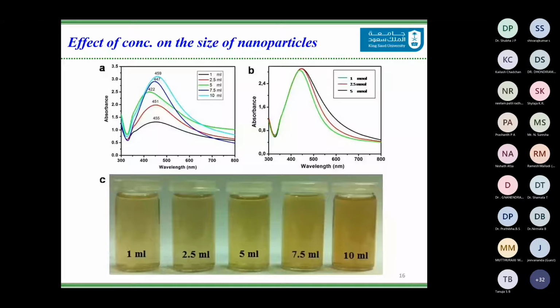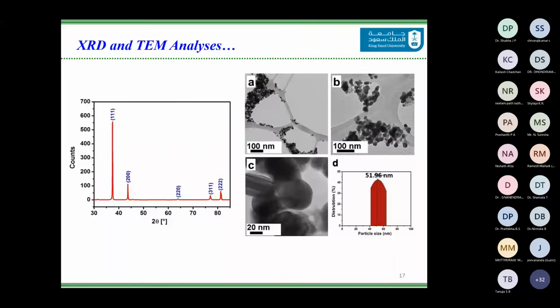Moving ahead, we subjected the obtained nanoparticles, which were isolated by centrifugation, to various other techniques such as XRD and TEM analysis. The XRD revealed that the silver nanoparticles we were working on were crystalline in nature. And the XRD pattern that we obtained revealed that the silver nanoparticles had a face-centered cubic structure.